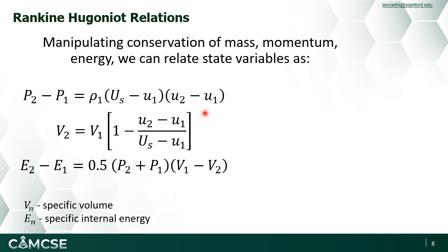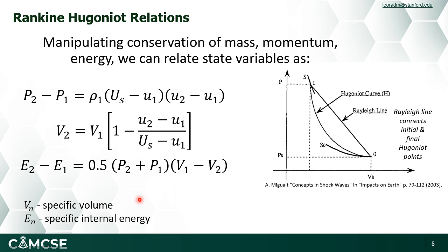So this is important because these velocities are actually measurable, as well as at least the initial density, meaning that it gives us the ability to take observable quantities and use those to get access to an understanding of the thermodynamic quantities required to describe our system.